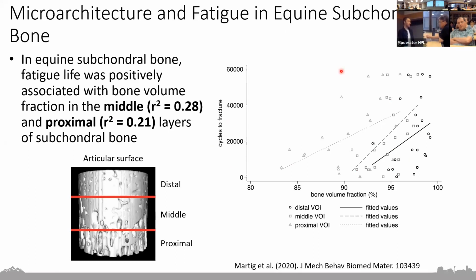And then looking at some work in equine subchondral bone specifically, again, it's been super limited. But there was one study that found fatigue life was positively associated with bone volume fraction in the proximal and middle regions of this subchondral bone sample. But really beyond this, there's been very little work trying to explore the mechanism behind these fetlock fractures.